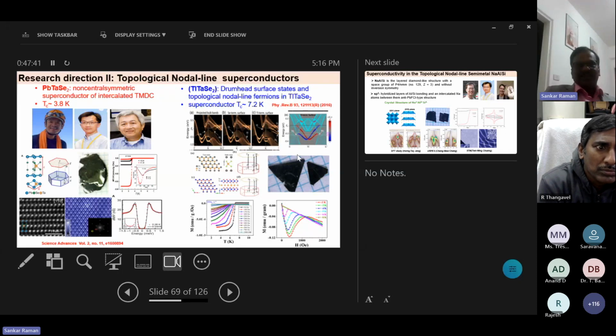I tried this crystal because it's really the first topological nodal line superconducting material. The transition temperature is 3.8 Kelvin. At that time we faced two problems. One is that the same material has two space groups, and we need the non-centrosymmetric one. Another thing is that if we use a normal transport agent like chlorine, iodine, or bromine, we cannot grow the crystal because it always forms tantalum diselenide.